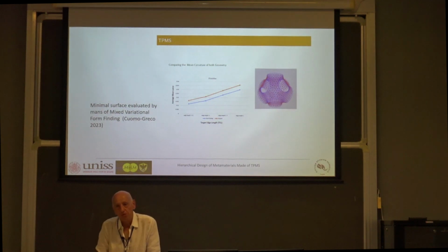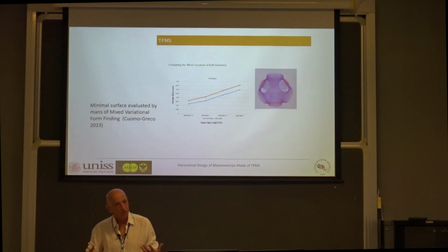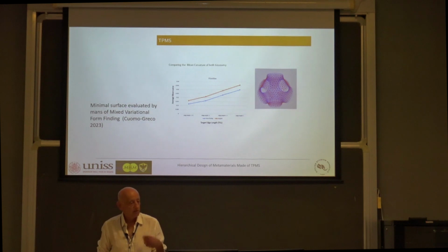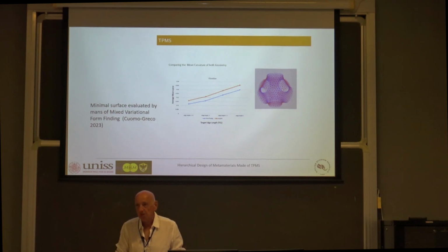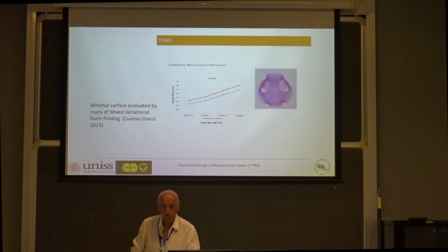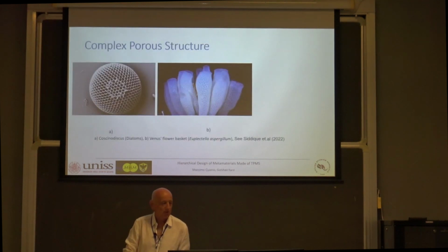Anyway, we have to be careful because even when we set the level parameter to 0, we do not get exactly a minimal surface. This shows the area functional measured on a discretized mesh. The red line is the one we get with the equation, and the blue line is the one we get from our form-finding variational method, so it's somewhat different. Not by much, but it makes some difference. It is possible to take the minimal surface, convert it to STL format, and use it for printing.